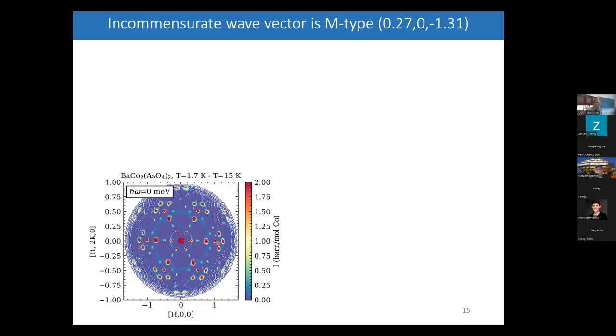Now, you might say, how is that possible? He mentioned that there was an out-of-plane wave vector component as well. Well, it turns out that our resolution is such that we can still pick up some diffraction as a result of some broadening of the peak along the L direction. So we still see it when we look at nominally the basal plane. We still see these six reflections.